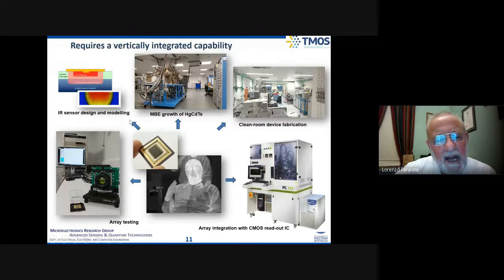So in our particular case, we have what's unusual for a university: a vertically integrated capability where we can undertake infrared sensor design and modeling. We have a very sophisticated device simulation package for mercury cadmium telluride infrared sensor design. We can grow the material in our MBE lab, take it up into our clean room and fabricate infrared imaging arrays, then package them using a flip chip bonder, which bonds the two-dimensional infrared imaging array onto a two-dimensional CMOS readout integrated circuit. Then we can package it out and test it on our focal plane array test system here.